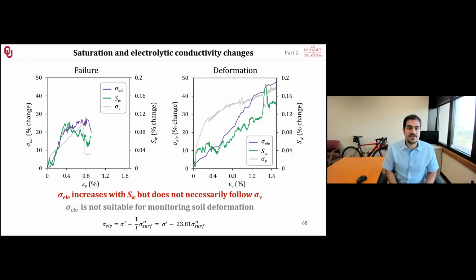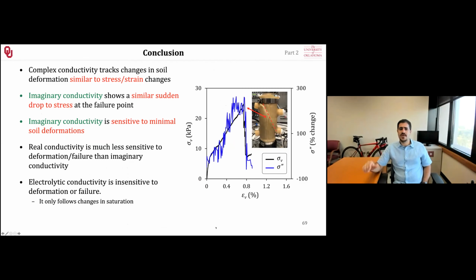The saturation and the electrolytic conductivity changes were unable to show any changes, unlike the imaginary conductivity, as expected, or as we talked about. So basically, with complex conductivity we are able to show the soil failure. Now, if we use that signal, we see kind of a flattening in here. This is a good indicator for future studies. If we reach this flat point in our signal, we could say, okay, soil failure is near, be careful.